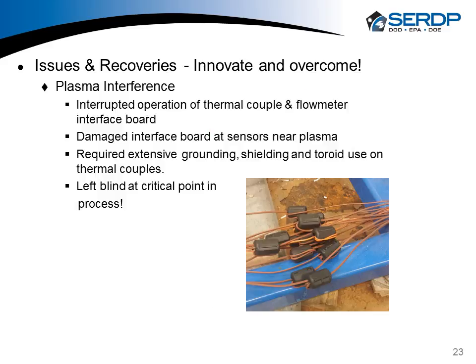The other issue, next one, was the plasma. The plasma runs at several thousand volts. I guess I should have known this, having worked where I have and run into a few EMI issues in my day. We noticed whenever we ran the plasma, when we started up, that the board wasn't taking any more data. And then when we shut everything down and started back up, we noticed that the thermocouples that were anywhere near the plasma were dead. The channel on the board that connected to those thermocouples was blown out. And if you think about it, a thermocouple was spitting out a millivolt reading, and your board is amplifying that and turning it into a digital output, and we damaged the board. So we wound up replacing the board.